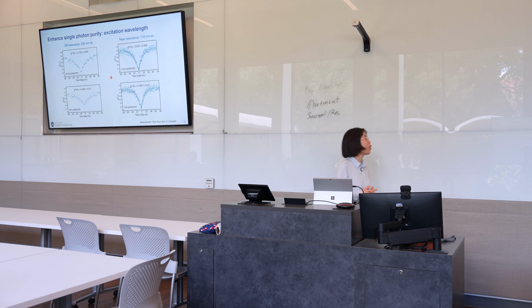All right, since now we're using the valley dichroism to achieve better single photon purity, we also know the valley dichroism depends on the excitation wavelengths. So can we further manipulate the excitation wavelengths to improve the single photon purity? With that in mind, we carried out an experiment with different excitation wavelengths, 520 nanometer, which is off resonance, and 718 nanometer, which is near resonance.